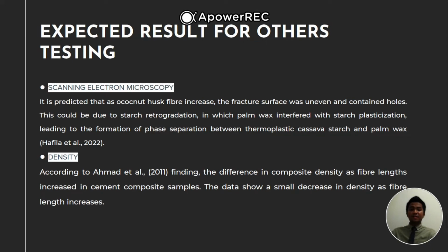Next, SEM. It is predicted that as coconut husk fiber increases, the fracture surface is uneven and contains holes. This could be due to starch retrogradation, in which palm wax interfered with starch plasticization, leading to the formation of phase separation between thermoplastic cassava starch and palm wax. For density, according to Ahmad's finding, there is a difference in composite density as fiber length increased in the cement composite sample. The data show a small decrease in density as fiber length increased.